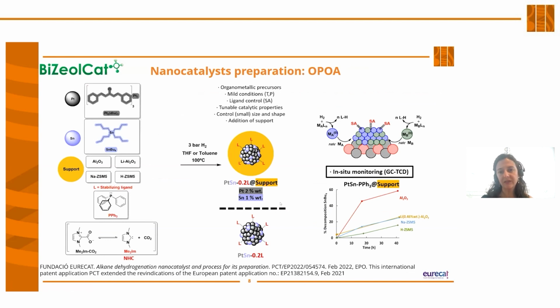The first one is the one developed in EURECAT, which is the one-pot organometallic approach. As you can see in the slide, what we did was, in the reactor, to mix the metallic precursors, platinum and tin, to prepare nanoparticles of platinum and tin onto the support. That could be, in this case, alumina or zeolites. We also use some ligands that act as stabilizing agents. So we place all together.